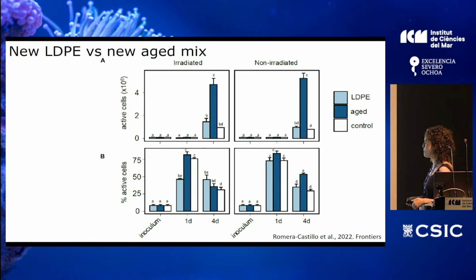So we have here the number of active cells in each treatment, and here the percentage of active cells in each one. Here we have the inoculum, then this is the result after 1 day of incubation, and this after 4 days of incubation. And we have the activity of bacteria grown in irradiated leachates and in non-irradiated leachates. We found that in the treatment with the aged plastic, the bacteria were more active after 4 days of incubation, both in light and dark. We didn't see significant differences here.